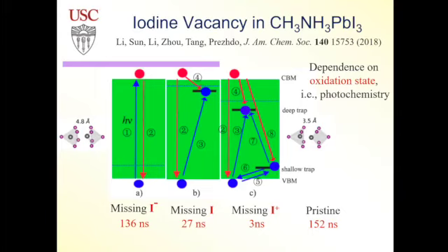What happens in this case, you have two lead atoms and you have iodine, used to be iodine between, and it's missing. So if you replace iodine with an electron now, it creates a bond. Before you had positive lead, negative iodine, positive lead in some structure. Now the iodine is missing, but if you have a charge, this electron in the middle attracts two leads and you make a dimer.